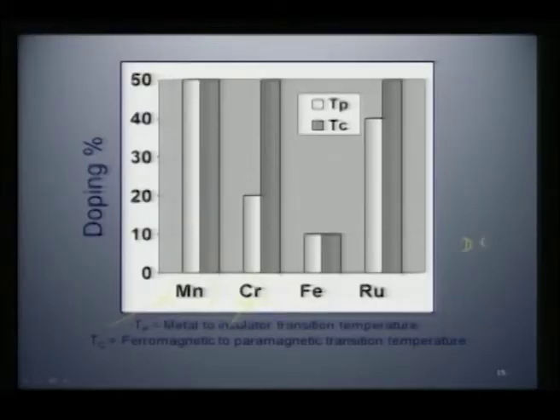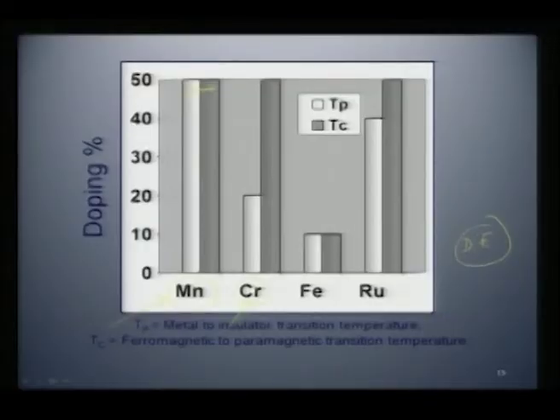But the real signature for a double exchange mediated ferromagnetism is that both the Tc and Tp, or the metal insulator transition, have to coexist like this. Both have to be like this if it is truly mediated by a double exchange model, but this is not happening in chromium. And if you see iron, as I showed you in the previous slide, both are killed at around 12%. Another interesting substitution comes from ruthenium.